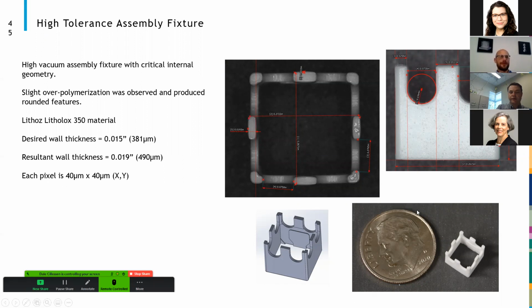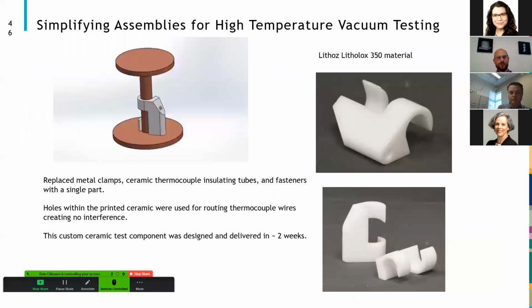But the critical feature for this is being evaluated by the design engineer, and it's actually on the internal of this component shown on the bottom right. You can see that little step within this, and the evaluation is being conducted to determine that it meets their fixturing needs. The rest of the geometry associated with this component was within the specification required by the design engineer.